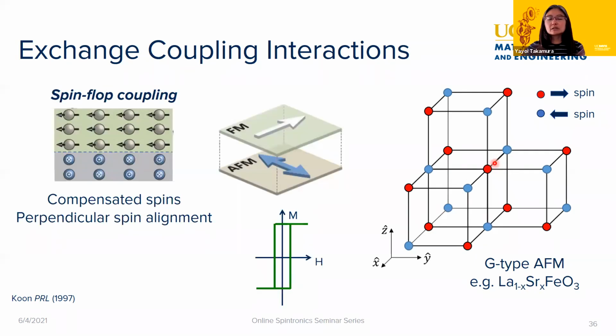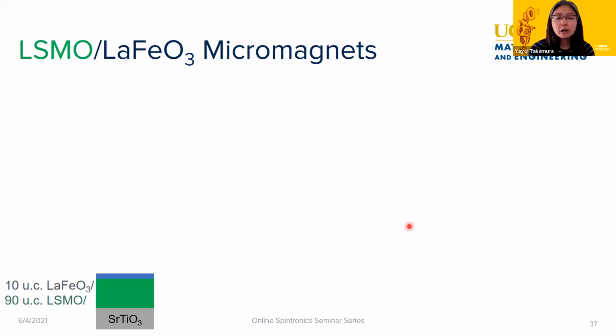And so the system gets frustrated, and instead of having that horizontal shifting of the hysteresis loop, the system minimizes its energy by having a perpendicular orientation between the ferromagnetic and antiferromagnetic layer, which is known as spin flop coupling. This is somewhat more difficult to analyze, at least through hysteresis loops, because you don't get that horizontal shifting. You might just see an increase in the coercive field because of the pinning that you still have between the antiferromagnetic and the ferromagnetic layer. And so we wanted to look for what kind of exchange interactions we might have.